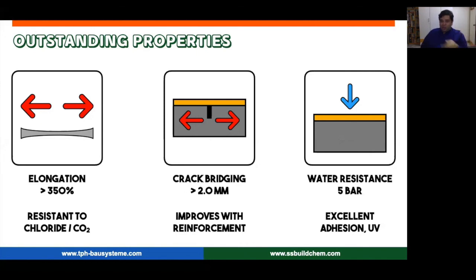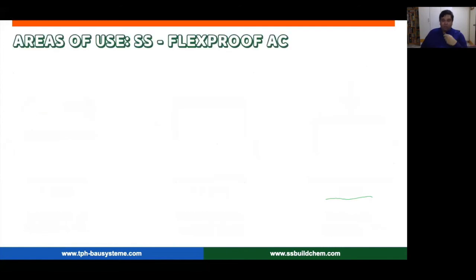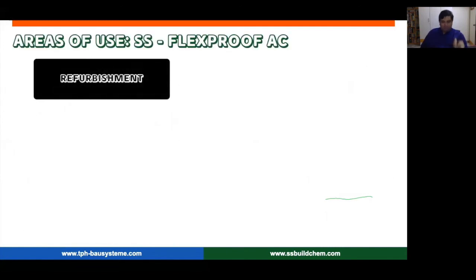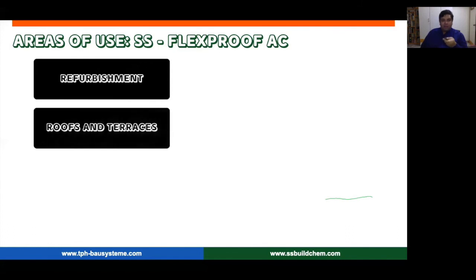You can even use it in areas like low traffic podiums, in terrace gardens and so on. And of course, being acrylic, it's resistant to chloride and carbon dioxide, and the properties improve with the reinforcement. We have seen that the tensile strength for this material goes from somewhere around 2 to almost 4.5 with reinforcement. That means it gets very tough. So it's a pretty good material to use in case of refurbishment.